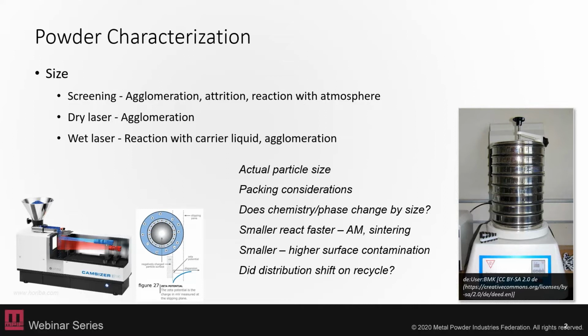And then you also have potential that if you're using a dry laser, you're exposed to atmosphere longer, and is that changing your agglomeration or your size distribution through reaction? Or with a wet laser system, as you're dispersing the powder in the fluid for it to be measured, is that powder going to react with your carrier liquid or agglomerate within that liquid? So you need to consider whether you're getting your actual particle size measurements and how these are going to change your packing considerations, whether you're going to get a nice uniform powder bed within your AM machine or nice flowability features. And we'll talk more about that in a little bit.